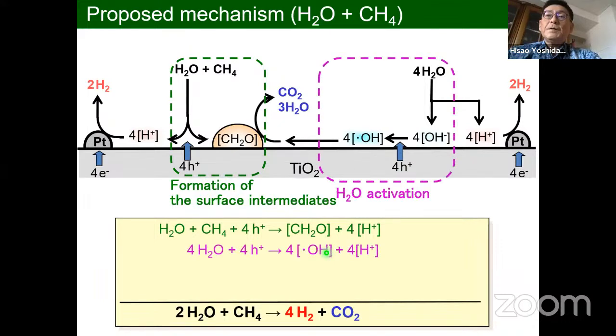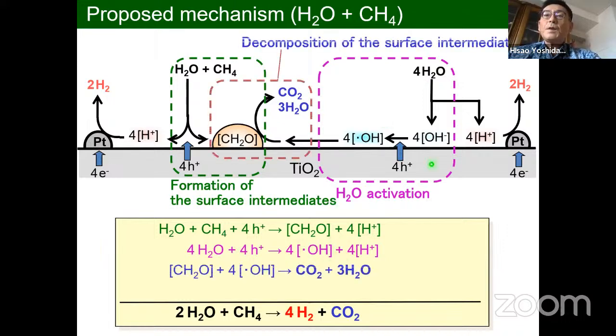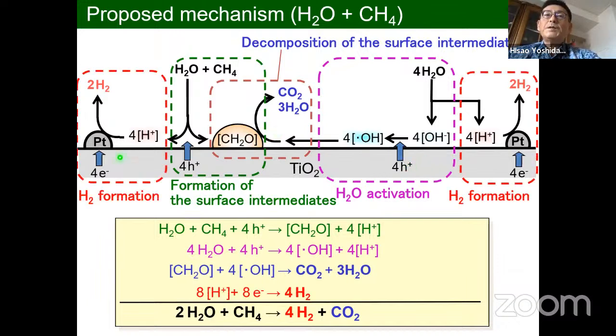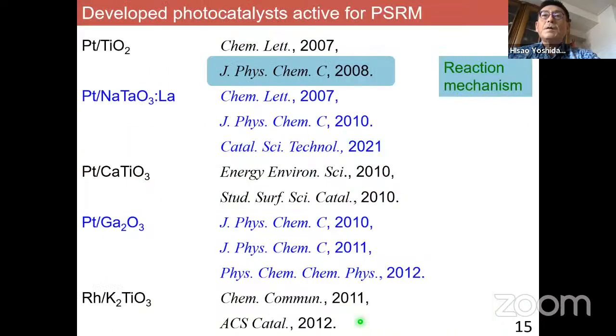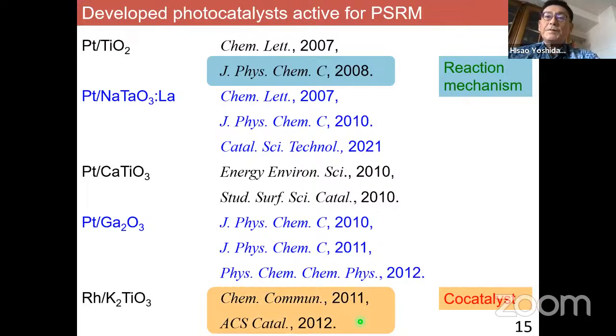After that, the water is also additionally oxidized to form OH radicals, and then the OH radicals attack the intermediates to form CO2. On the platinum side, on the titanium oxide, protons are reduced to hydrogen, so that we get 4 times hydrogen to carbon dioxide in this system by photocatalysis.